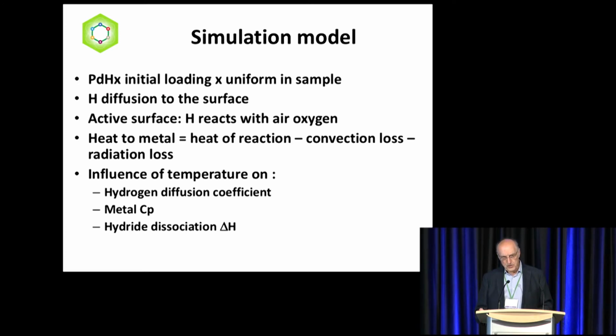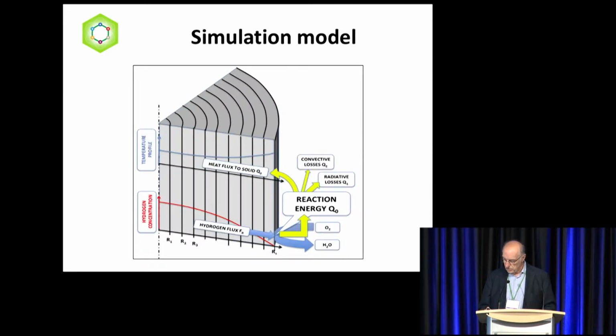The heat of reaction is split into a heat conducted inside into the metal, convection loss, and radiation loss. It's easy to calculate. And you have to take into account the influence of the temperature on the hydrogen diffusion coefficient. This is very important. The metal heat capacity, and also the hydride dissociation enthalpy. This is a picture explaining exactly what I said a few seconds ago.